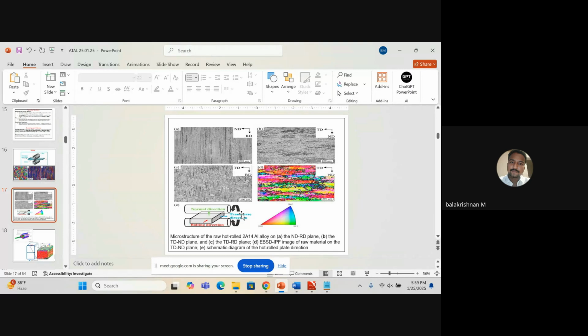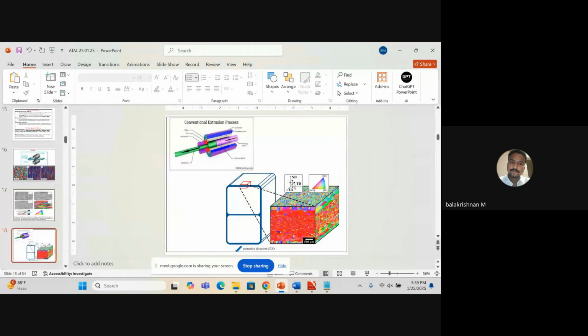Here is another example, hot rolled 2A14 aluminum alloy. In this case also we can see the normal direction, then the rolling direction, then the transverse direction. Here we can observe that the particles are agglomerated, not evenly distributed, due to the rolling process.